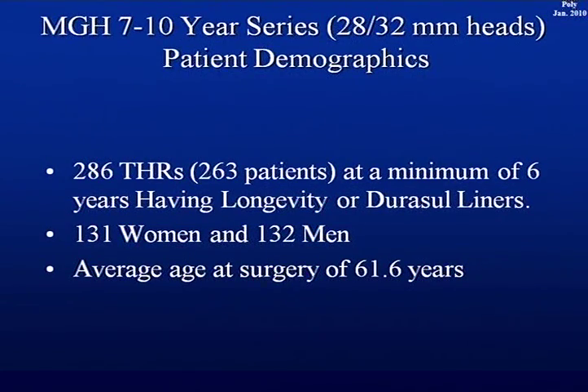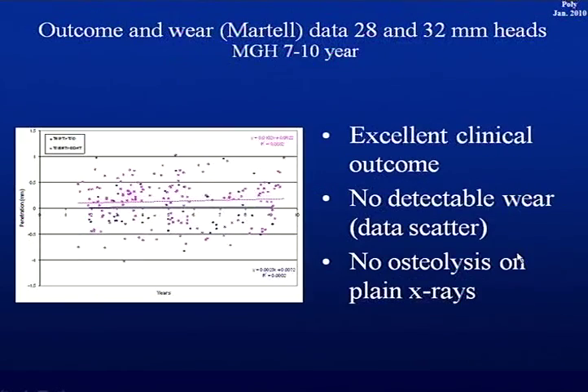So a brief summary: where are we on the highly cross-linked polyethylene with 28 and 32 millimeter heads? We had 286 patients for a minimum of 6 years follow-up, and the average age at surgery is 61.6 years. This is the outcome not measured by RSA, but measured by Martell, which typically shows up in a data scatter like this. And we can really see no inclination in the curve, indicating we can't detect wear using the Martell. But more importantly, there's no osteolysis in any patient on plain X-rays.